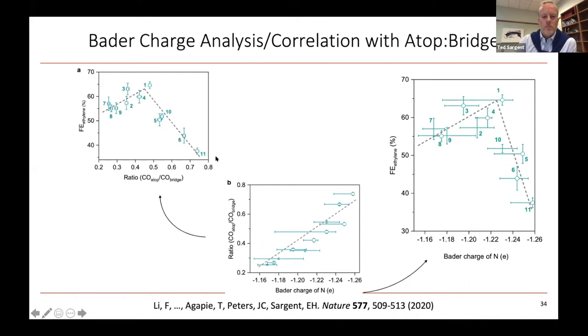And then with the aid of Raman, we could look at the ratio of atop to bridge, shown on the horizontal axis here. And then we calculated the Bader charge on the nitrogen, shown on the horizontal axis in the middle, in the rightmost figure. You'll see that by tuning the designed Bader charge, we were able to tune the atop to bridge experimentally observed ratio from Raman.